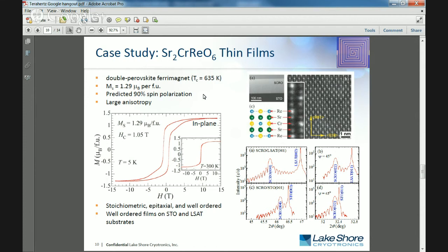But what we wanted to do was use terahertz spectroscopy to measure the properties of thin films. These are 20 nanometer to micron thick films of this material. And we wanted to see what we could learn about the carrier mobilities in these materials, especially with temperature.